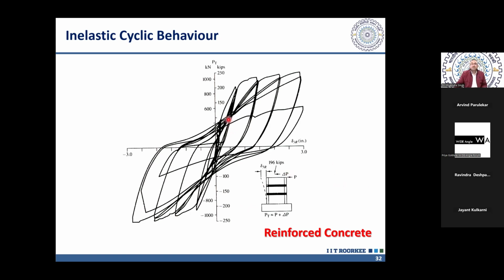That is one problem. Another problem is that at the same displacement under different cycles, the strength goes on reducing. So you can see in the first cycle here, the strength is this much. Next cycle, it is this much. Next cycle, it is this much. Next cycle, it is further down, further down. So even at the same displacement, the strength goes on reducing. This is called cyclic degradation of strength and stiffness. So under cyclic load, the stiffness also reduces in successive cycles. The strength also reduces in successive cycles.